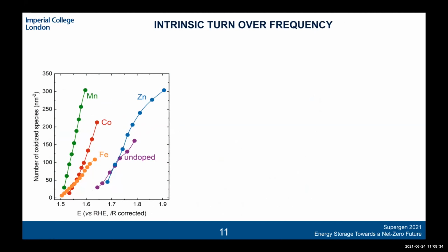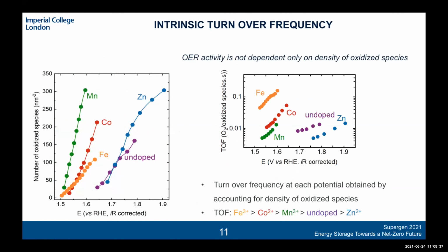So based on all of this information, what we can do is also quantify a turnover frequency, which is an intrinsic measure of the amount of oxygen that's produced per density of these oxidized species per second. And interestingly, here again, we see that the iron doped oxide has much faster kinetics at a given potential. And while it's the manganese doped catalyst that can produce these oxidized species quite readily, its intrinsic kinetics to oxidize water is much slower.